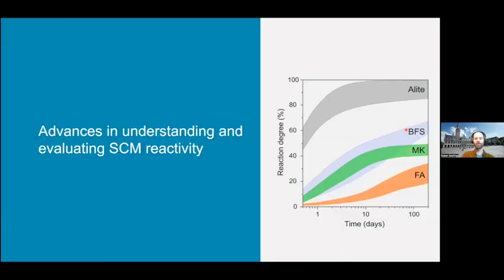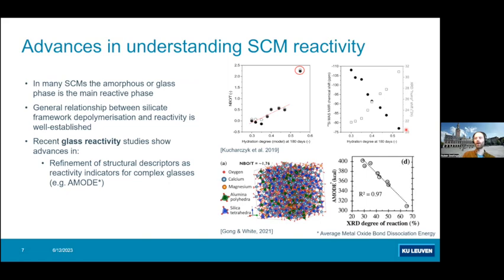Before we dive into some of the materials themselves, I think it's also good to highlight a few of the advances in understanding and evaluating SCM reactivity. With today's advancements in methods, for instance, in molecular modeling and so on, we've come to a deeper understanding. Of course, we already knew that reactivity in SCMs in many cases is linked to amorphous phases being present, or the composition of a certain glass phase, which then eventually is linked to something like the silicate framework structure, whether it's more depolymerized, whether it's less depolymerized, whether there's more calcium in there, whether there's more silica in there, and so on. This is fairly well established, and it's also embodied in many of the standards.